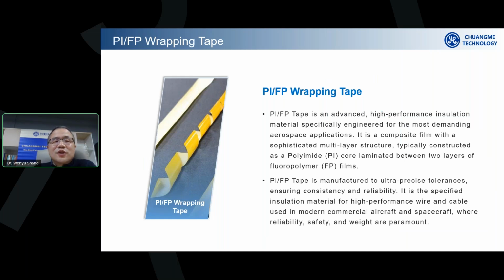But the most important factor is very simple, because the airplane is getting even faster. The airplane flies even higher. So they demand even higher temperature. So the third generation with XL-ETFE material can sustain 200 degrees C, right? Some of the communication cables on the plane demand even higher temperature, up to 260. So that is 60 degrees C higher than the third generation. This is why the industry developed this polyimide composite wrapping tape solution.